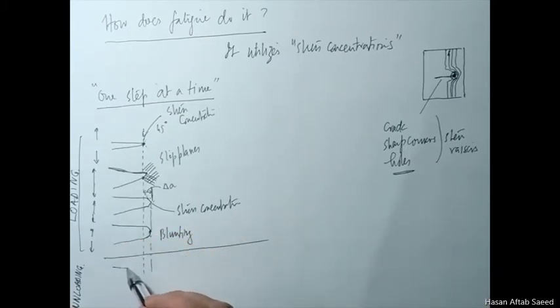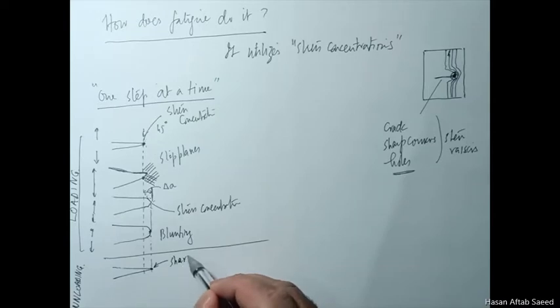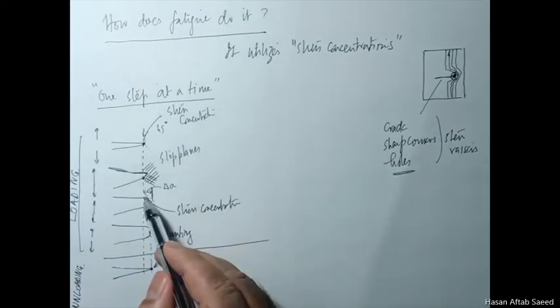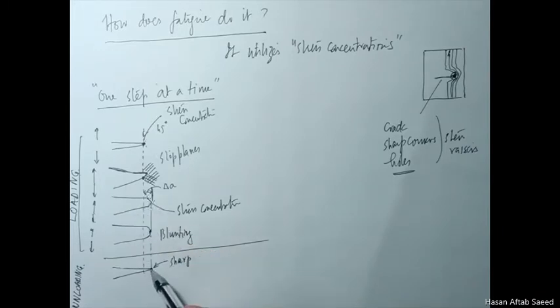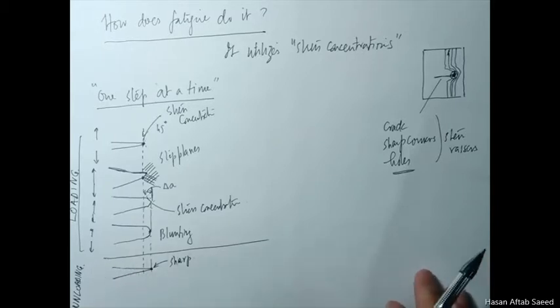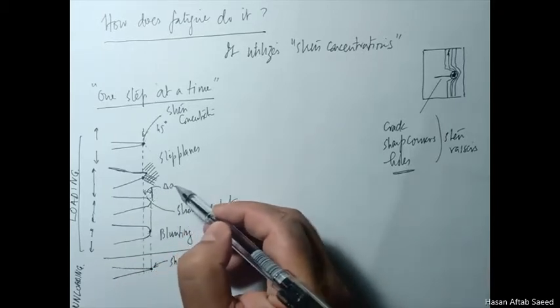This thing again becomes like this, again sharp. Hence, again there is stress concentration. So what happens is, as a result of one cycle of loading and unloading, the crack has extended by some small amount. And what's more, if it was just static loading, then it doesn't make a difference. This is maybe an atomic distance, one bond distance.